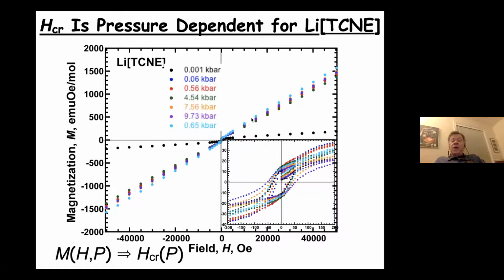Now we're looking at the pressure dependence, and in this slide, we're just simply going to show the pressure dependence of the hysteresis loops. You can see not much changes globally from virtually ambient pressure up to 9.73 kilobars, and even going back to almost ambient pressure. But you can see in the inset in the bottom right that in fact there is a change in the coercivity of it.